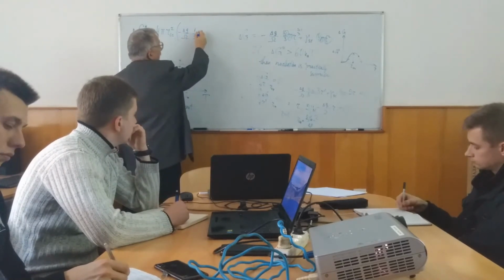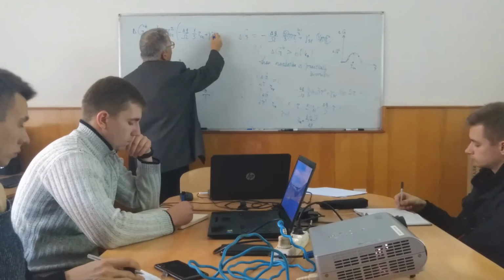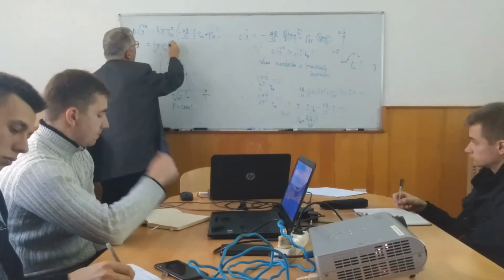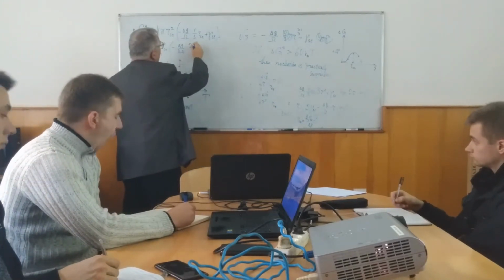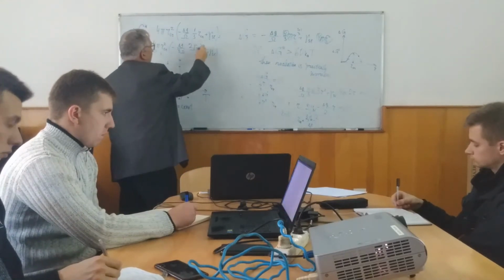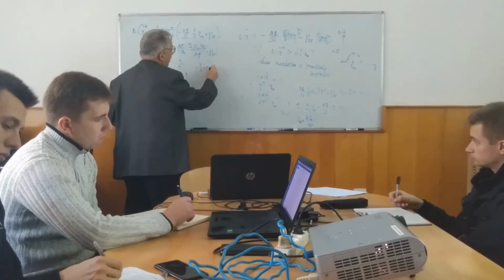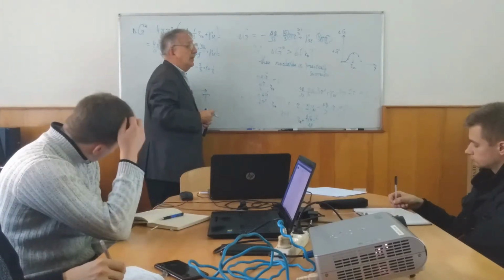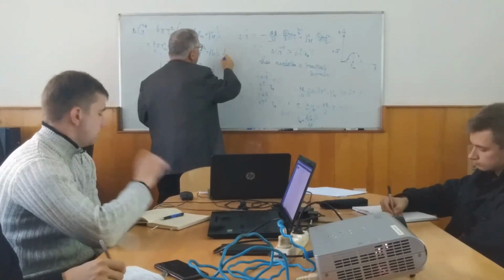So under the parentheses, we have minus delta G divided by omega, multiplied by 1 third, multiplied by R critical, the rest is here, plus gamma SL. And it's equal to 4 pi R critical squared multiplied by minus delta G over 3 omega multiplied by R critical, which is here, 2 gamma SL omega divided by delta G, plus gamma SL. Of course, omega cancels, delta G cancels, and minus 2 thirds plus 1 is just 1 third. And so we have the famous equation, which doesn't depend on the shape. It can be proved, but I never proved it in general case, but I proved it many times for some special shapes. So it's 1 third gamma SL